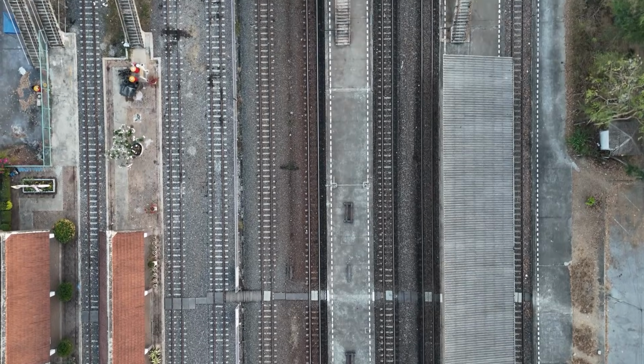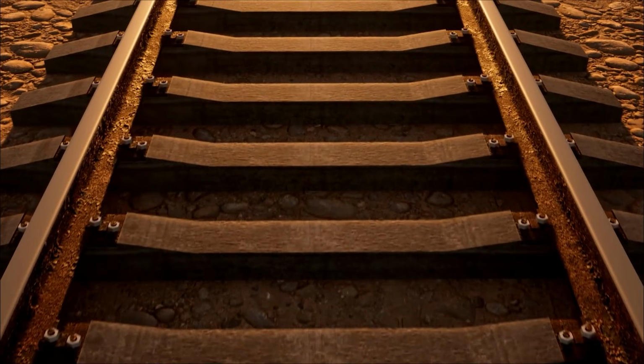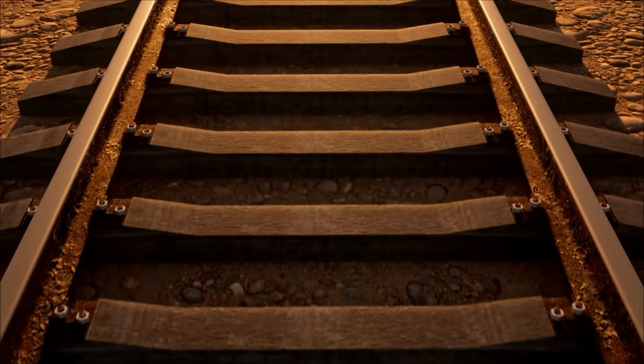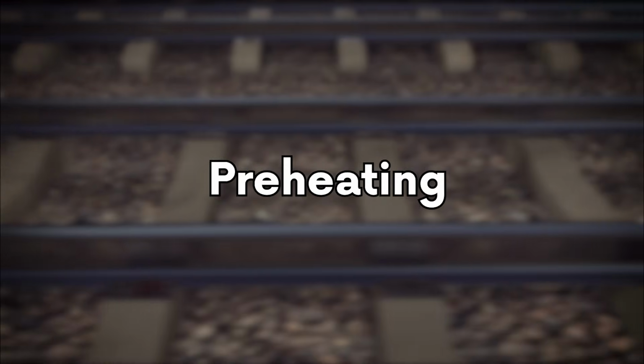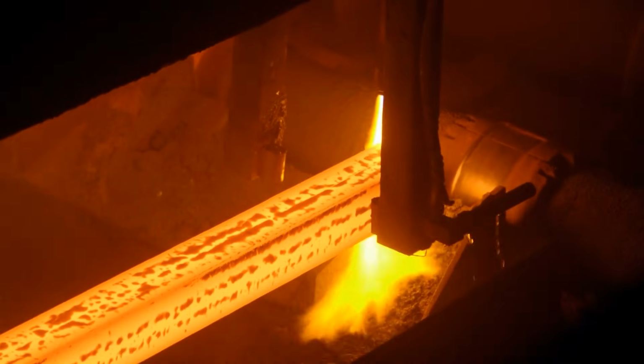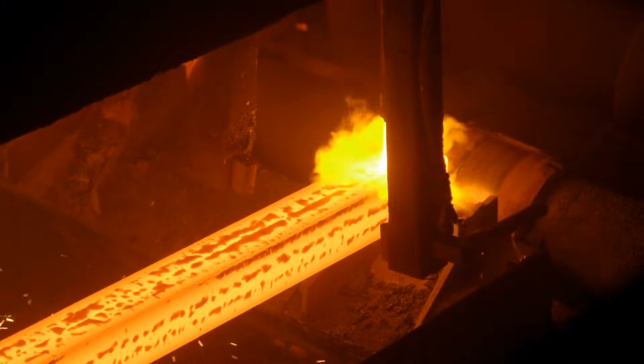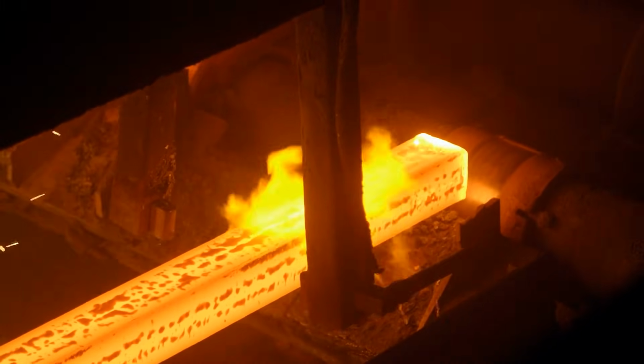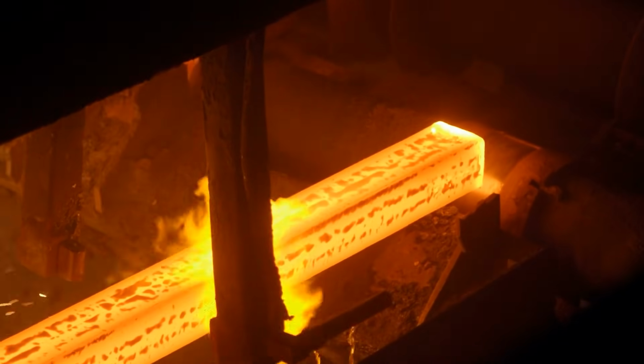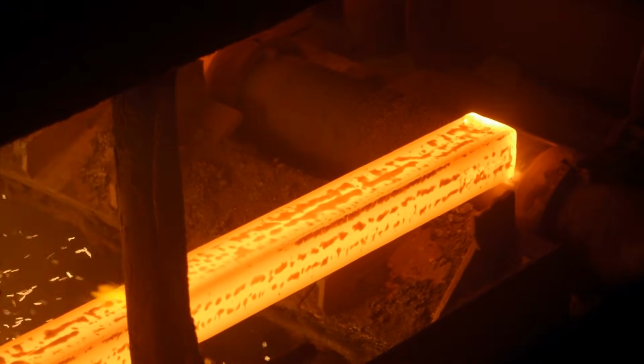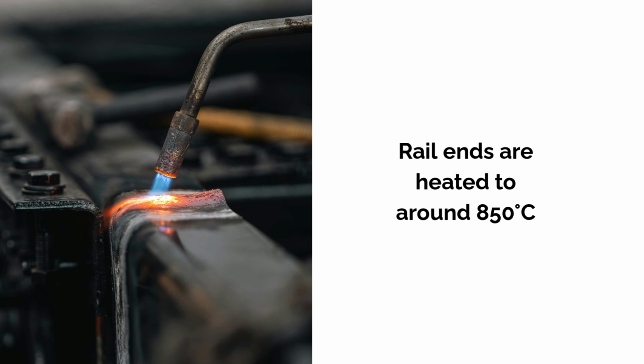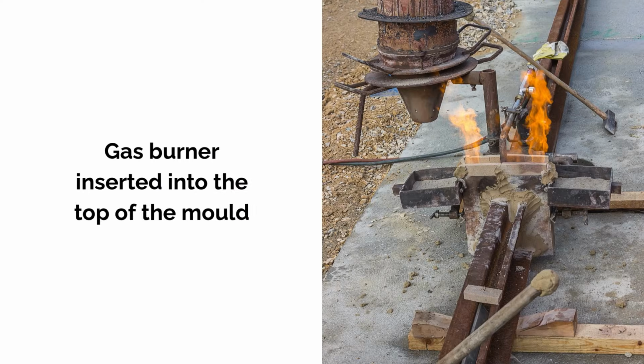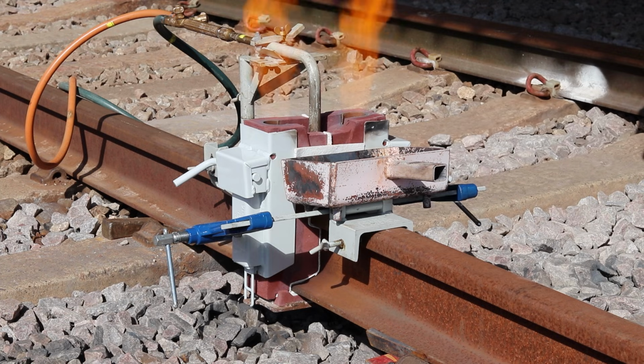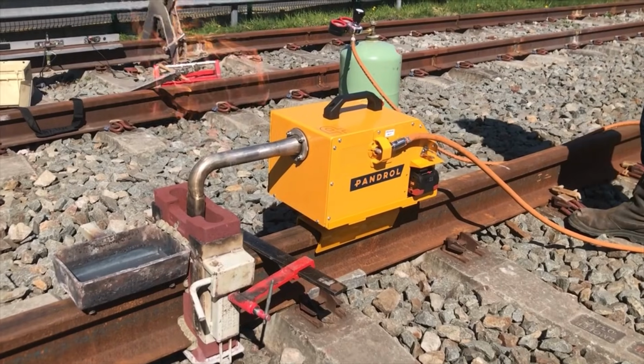Once a mould is fitted and sealed, the focus shifts to temperature, because the rail has to be prepared before any molten steel is introduced. Steel expands rapidly under heat, which means if it's hit with molten metal while cold, the temperature difference can cause cracking before the weld even forms. That's why welders preheat both rail ends to around 850 degrees before the pouring. They use a gas burner inserted into the top of the mould, using a specially designed nozzle that directs heat evenly around the rail head and web. Preheating continues for several minutes, depending on the outside temperature and the heating equipment being used.